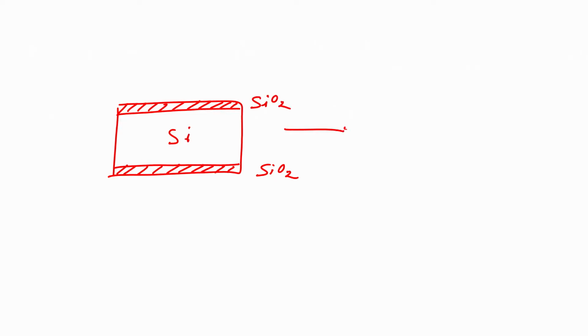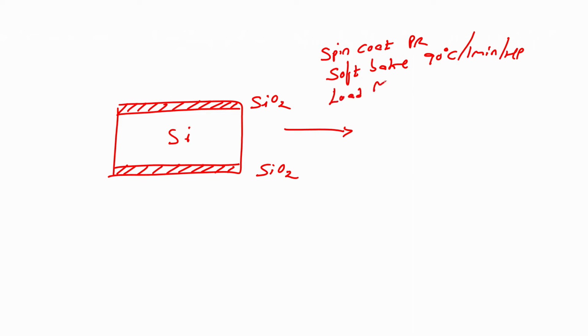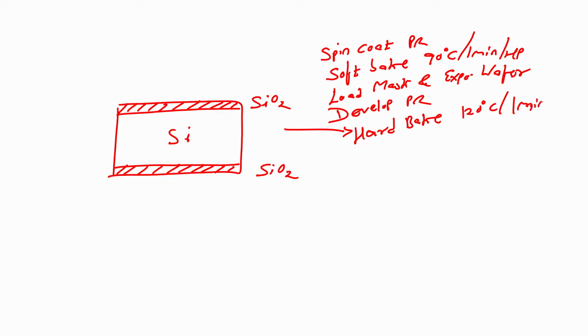Now, if I go for photolithography, which you know how to do, right. Spin coat photoresist, then soft bake. Soft bake is done at 90 degrees centigrade for 1 minute on a hot plate. Next step is you load the mask and expose the wafer which is spin coated with photoresist. Next step is you develop the photoresist. After that you hard bake. Hard bake is done at 120 degrees centigrade for 1 minute on a hot plate, followed by inspection.